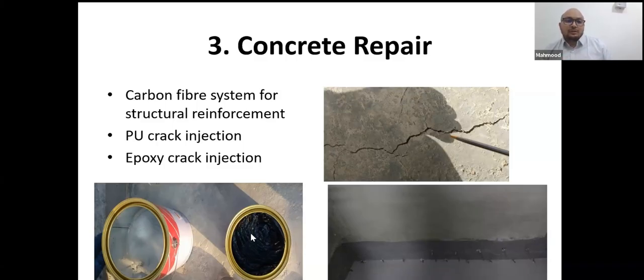This is epoxy paste. It's a putty actually. Base and hardener, they mix it. For injection, they're fixing injection nipples and they close the crack with a thick band of epoxy putty, and they inject with the epoxy resin, which is low viscous, the same as water. The viscosity is to fill the crack and to treat the structural crack.